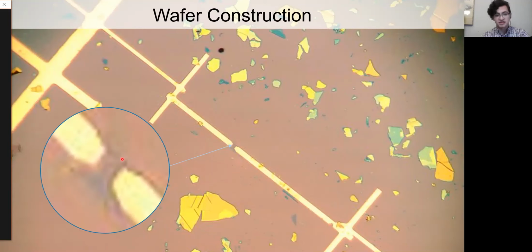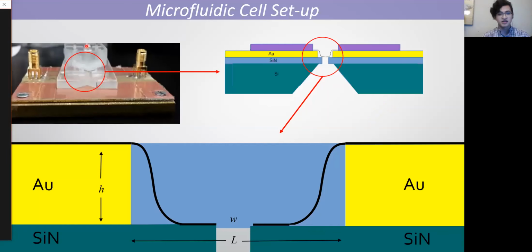This wafer assembly is done entirely underwater in our microfluidic cell. The microfluidic cell gets the wafer placed directly in the middle, and it gets submerged into water. This is done to avoid any bubbles, even micro and nano bubbles. These bubbles, if found, will cause us to misread the resistance of the ionic current, which will lead us to have faulty results. And so it's extremely crucial for us to submerge our devices and make sure that we have